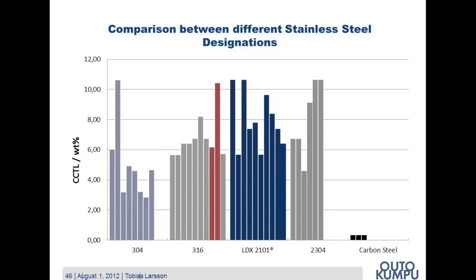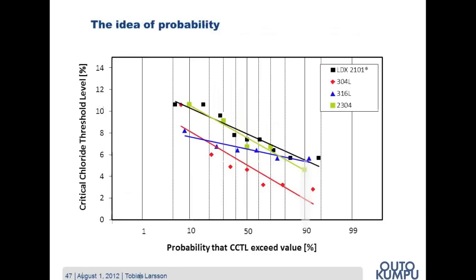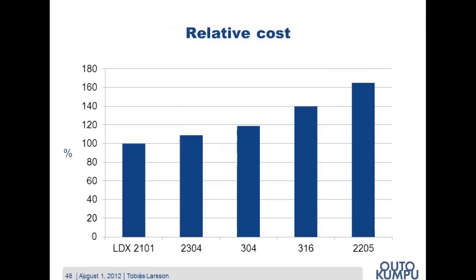The austenitic grade 316 and the lean duplex grades LDX 2101 and 2304 perform more or less on the same level, while the 304 values are a bit lower. However, you can also see that there is a big scatter in the results. Therefore, we think it is better to use the idea of probability. This graph shows that there is a 90% probability of LDX 2101, 316L, and 2304 rebar achieving a critical chloride threshold level given about 6% chlorides by mass of cement. And this figure drops to about 2% for the 304L.